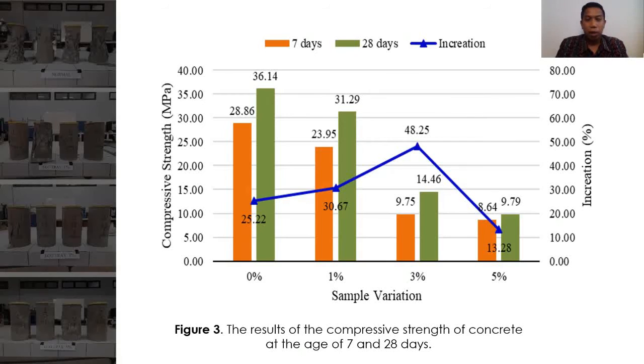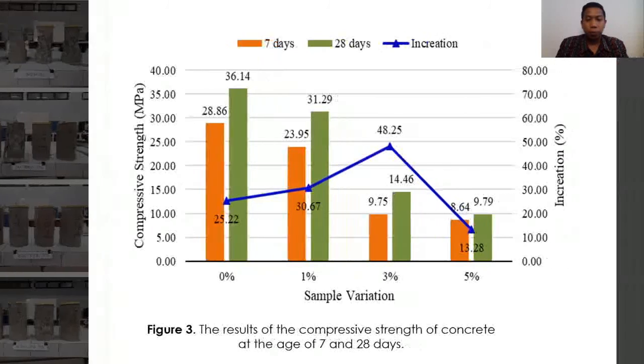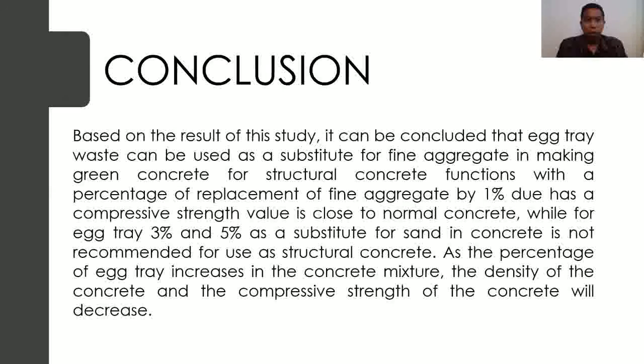and 9.79 megapascal. Generally, there is an increase in the compressive strength of concrete from the age of 7 days to the age of 28 days. For the normal concrete, the increase in the compressive strength of concrete is 25.22%, while the increase in the compressive strength is more significant at 3% variation, which is 48.25%. In the variation of 1% and 5% egg tray, the compressive strength of concrete increased by 30.67% and 13.28%.